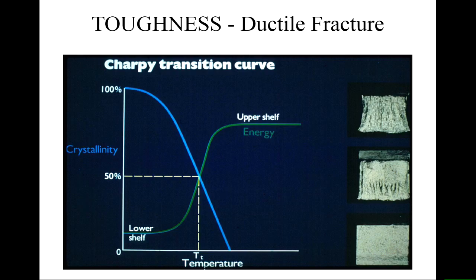So what you see here are Charpy tests, and they don't look too different from the drop weight tear test results. This is a brittle failure at low temperature. This is a mixed failure with a brittle piece here and a ductile piece here, and the top one is a fully ductile failure.